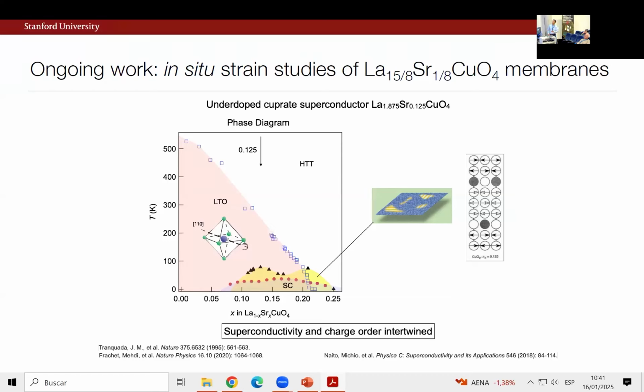So let me briefly introduce, or reintroduce, to many of you, this long-standing issue in cuprates. Namely, if you look at the 214 cuprates, there's a glitch in superconductivity. If you go from strontium to barium, this goes all the way to 0, for example. But you have an anomaly particularly prominent at 1/8 doping. And it's been understood to come from a competition with a competing stripe-like instability, okay? And so this has been, including using strain, a subject of much discussion and research interest in the past few years.